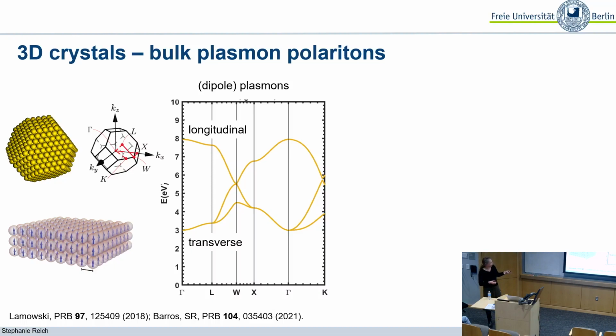There's one longitudinal plasmon where the electric field is polarized along the propagation direction. It's important to realize that the electrons that make up this excitation are all confined and localized to each nanoparticle, so they cannot move through the crystal, in contrast to a bulk metal, but the plasmon is able to propagate the excitation through the entire crystal. This longitudinal excitation you would also get in bulk gold, but what you would not get is a transverse mode. In these supercrystals, because the electrons are bound to the nanoparticles, we also get a transverse plasmon excitation. Now this simulation considered only the dipoles in the nanoparticles, not the interaction with far-field photons.